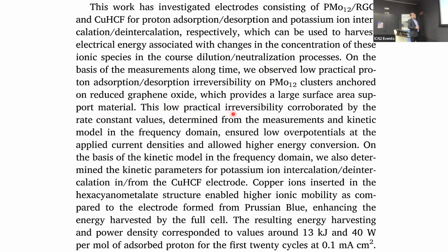This low practical irreversibility is corroborated by the rate constant values determined from the measurement and kinetic model in the frequency domain. And so in the end, the resulting energy harvest and power density corresponded to values around 13 kilojoules and 40 watts per mole of adsorbed proton.